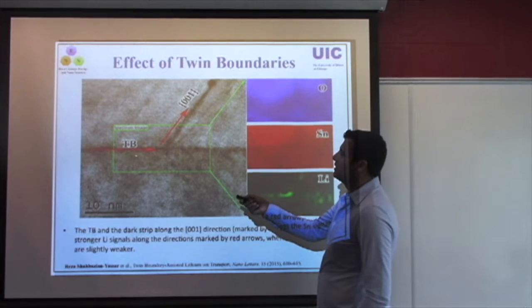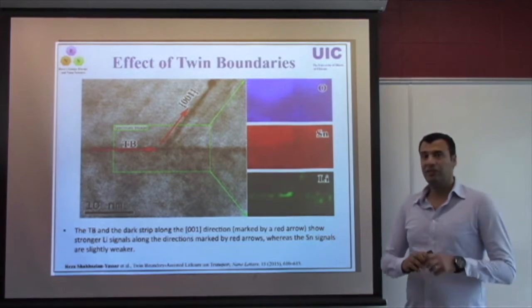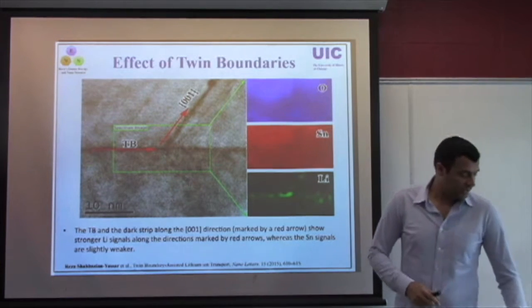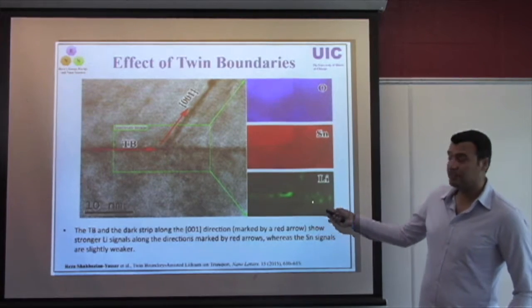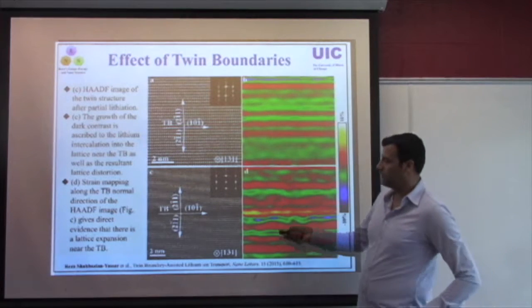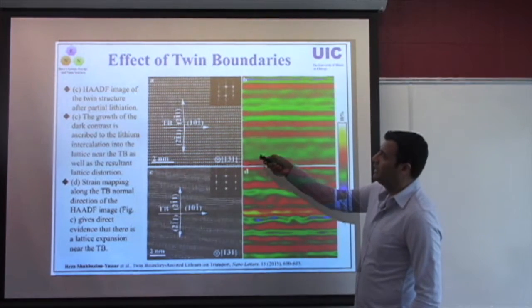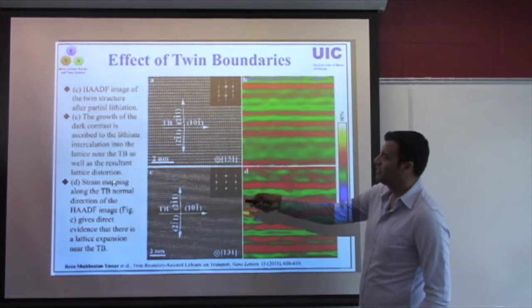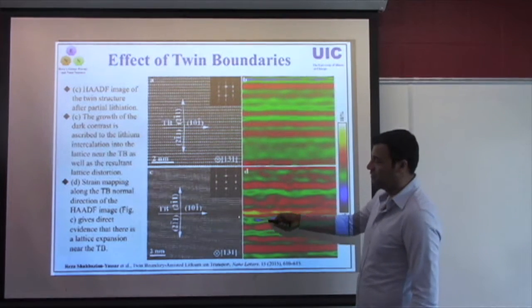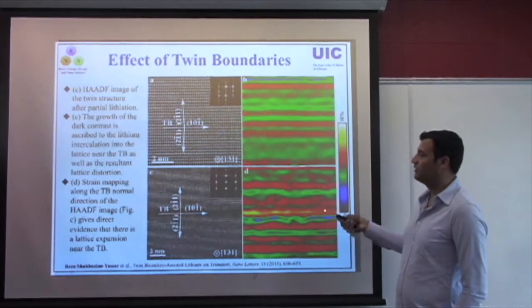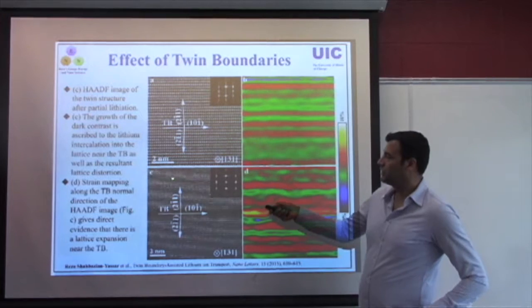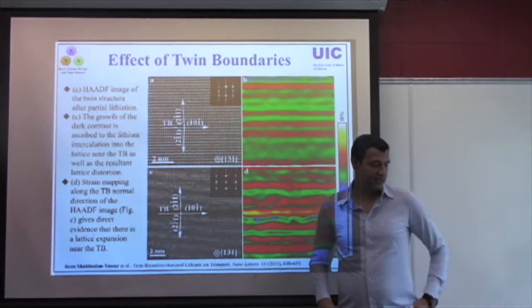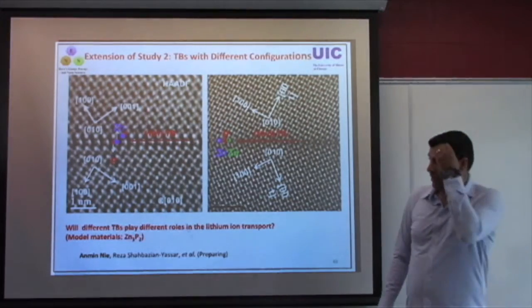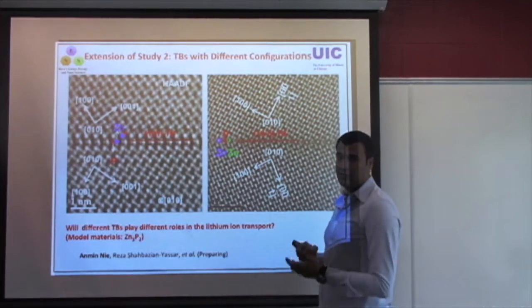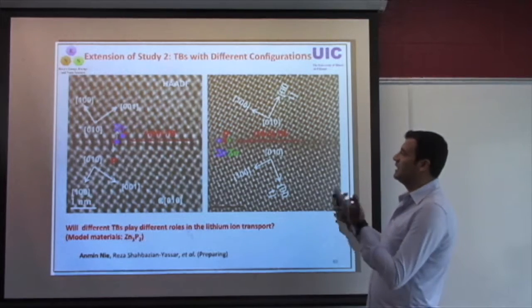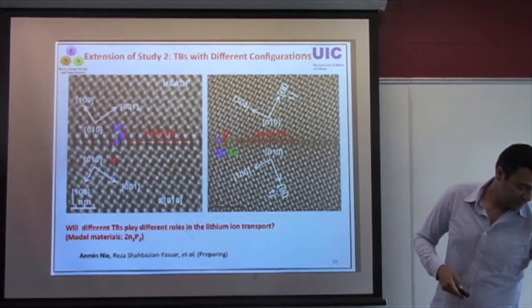Something we learned from this experiment was that these twin boundaries are accommodating channels for the lithium to be transported through. We could confirm that by the EELS analysis at very small scales. This image shows an example of a twin boundary, and lithium is transporting through this area. Right before the transport of lithium, this area shows a significant change in the contrast associated with stress formation, which indicates that among all the directions that exist in this sample, the twin boundary direction is the preferred direction for the lithium to move into. And this could bring a lot of questions about what the character of the twin boundary should be to allow faster progress of the lithium, as well as a variety of characters and misorientation behavior that need to be investigated.